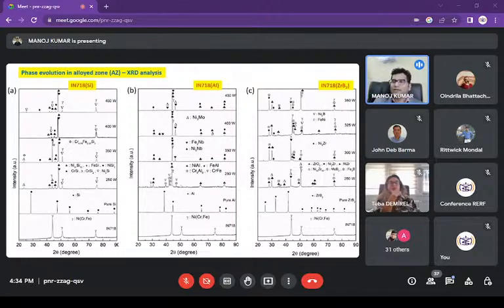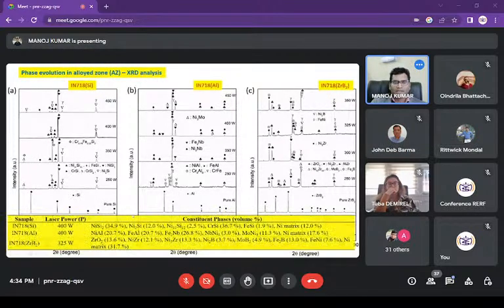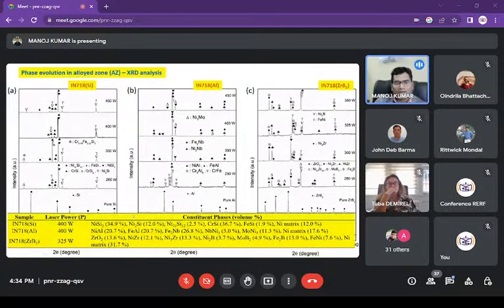So we carried out a very extensive phase analysis, phase evolution during the laser processing for all the three cases when we alloyed with silicon, aluminum, and ZrB2, and we find that almost 30 to 45%, or if you add together, almost 50% of the silicides are formed on the top surface when we alloy with silicon. And a similar story goes for aluminum and ZrB2.